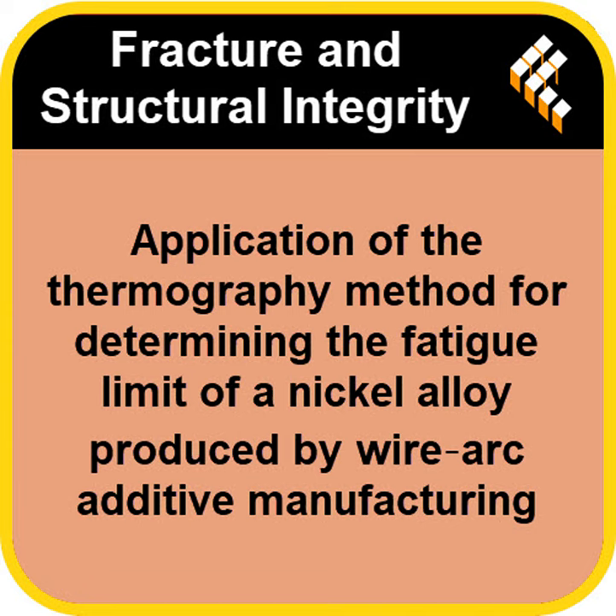So it's very efficient, but I'm guessing that layering process can cause some issues. It's not the same as a single solid block of forged metal. Not at all. The thermal history, all that constant heating and cooling of the different layers, can introduce microstructural flaws or tiny pores that can really compromise the strength. Which means post-processing is everything. You can't just print it and put it in a plane.